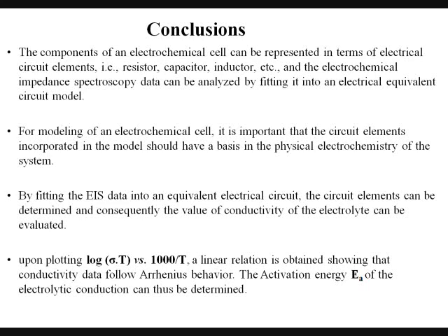By fitting the EIS data into an equivalent electrical circuit, the circuit elements can be determined and consequently the value of conductivity of the electrolyte can be evaluated. Upon plotting log sigma T versus 1000 by T, a linear relation is obtained showing that the conductivity data follows Arrhenius behavior. The activation energy EA of the electrolytic conduction can thus be determined.